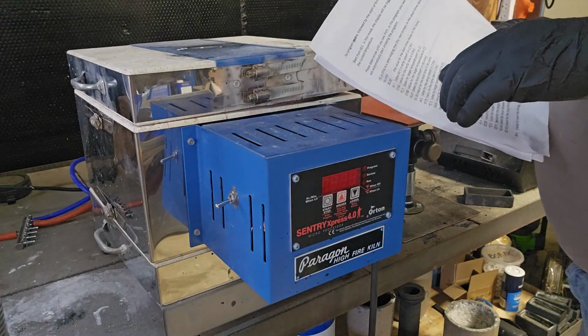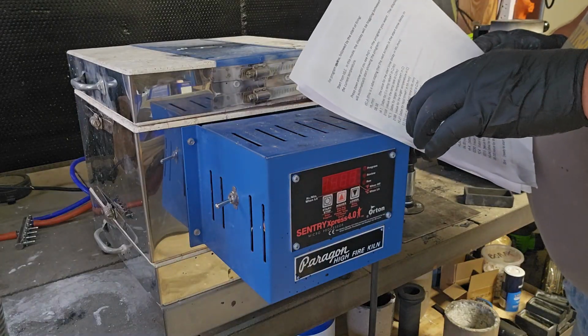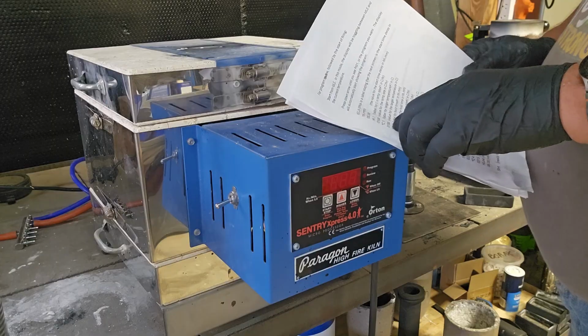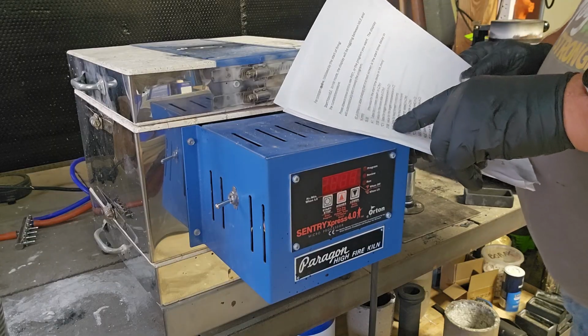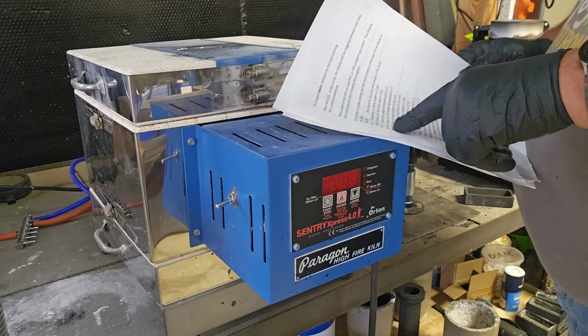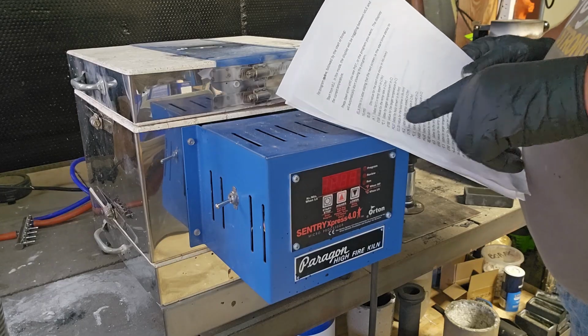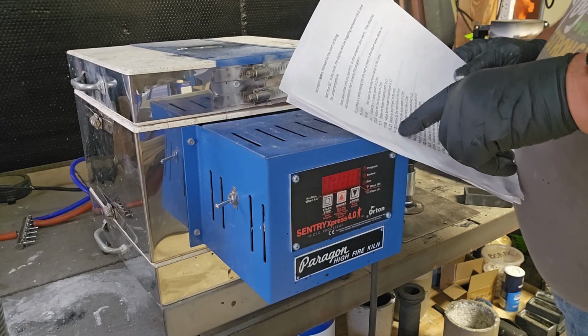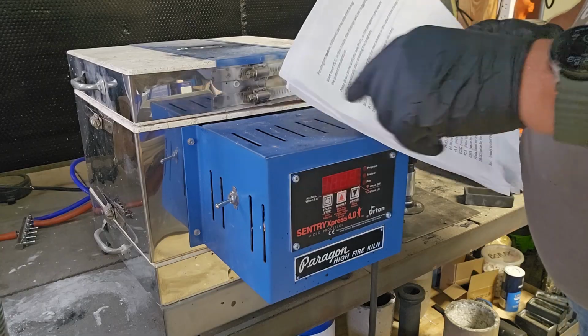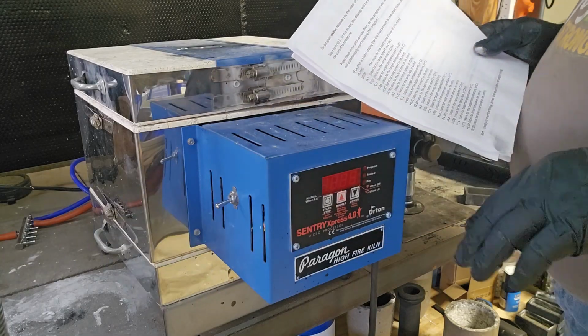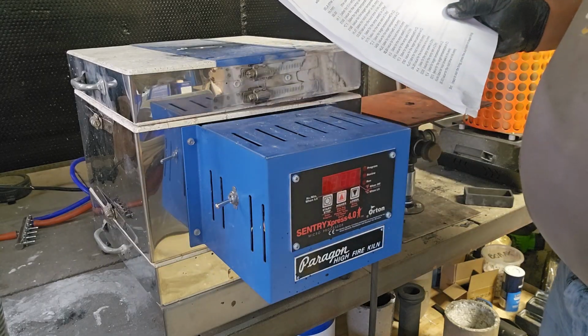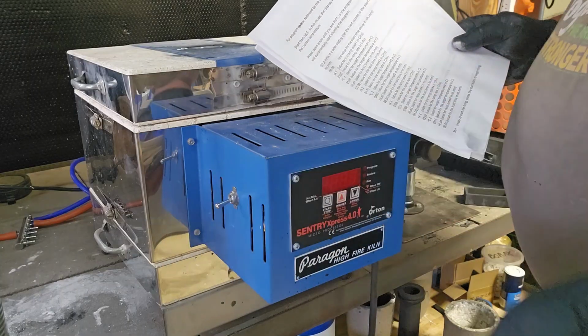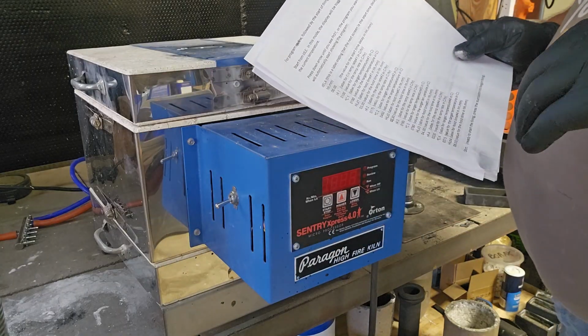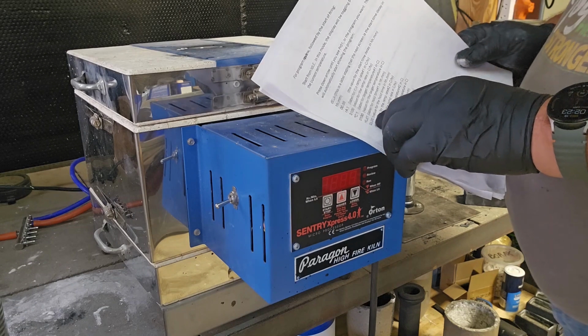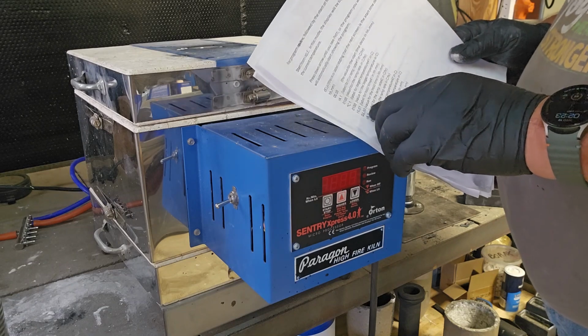We ramp the temperature up at 100 degrees C an hour until it gets to 100 degrees C, and 100 degrees is where it boils water. So you leave it at 100 degrees C for 3 hours, and that gets all the water out of the plaster. If you heated it up too much, too quickly, that water would turn to steam and explode the plaster. So 3 hours of soak at 100 C.